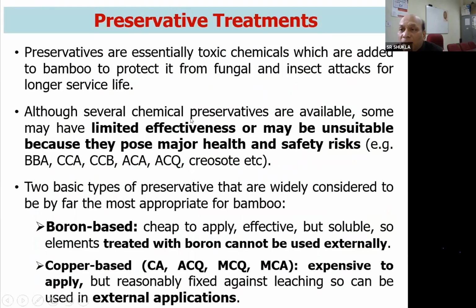The second processing is the preservative treatment of bamboo. Because bamboo doesn't have any toxic chemicals, we have to inject toxic chemicals into bamboo to protect it from fungal and insect attack. There are many chemicals available, but some may be useful and some may not be useful in the case of bamboo. There are two types of chemicals. One is the boron-based, and another is the copper-based preservative chemicals. Boron-based chemicals are cheap to apply, effective, but soluble in water. So when we have to use the bamboo in rain-fed areas, or particularly where water availability is more, we should avoid using the boron-based compounds.